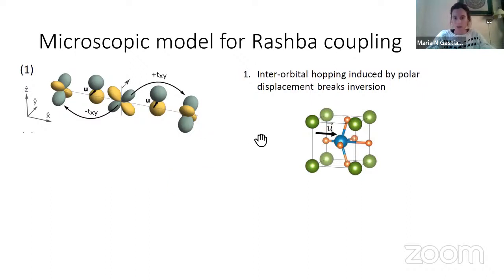The first step is once I shift the oxygen cage with respect to the titanium, which is shown here. The oxygens have this p orbital. Once I shift this to a finite polar displacement, there is a new hopping channel allowed between the different orbitals. If u is equal to 0, if there is no polar displacement, then by symmetry you can't have a hopping between these yz and xz t2g orbitals. So this interorbital channel would be forbidden. Once you break this mirror symmetry, that is no longer the case, and you can have a hopping.